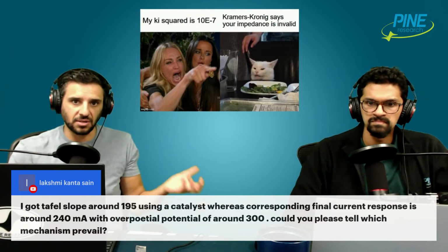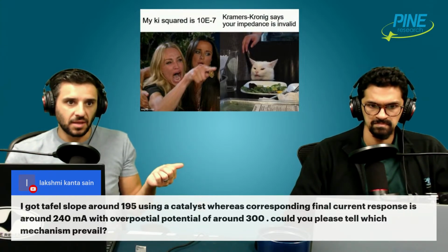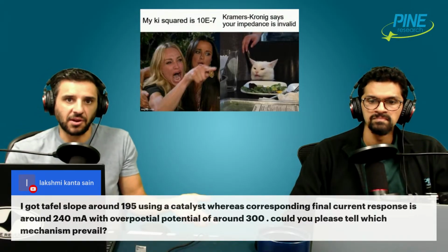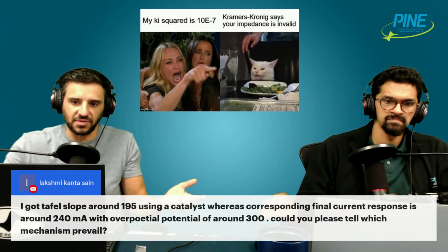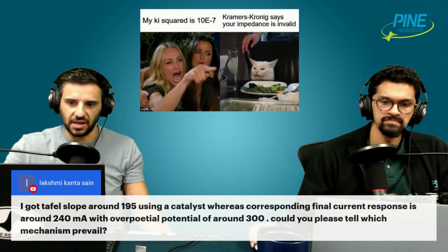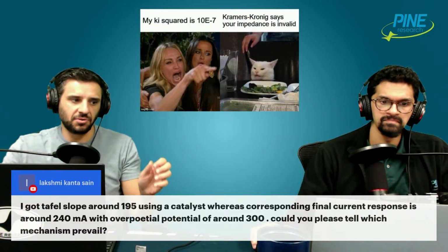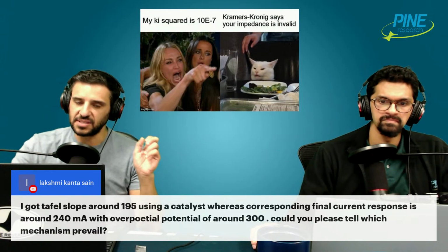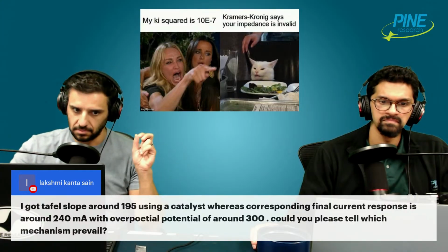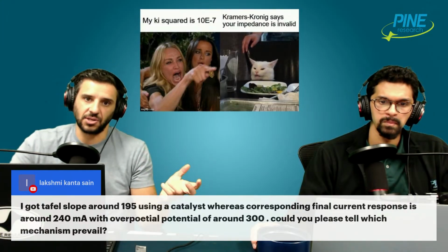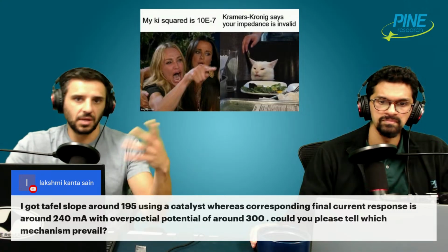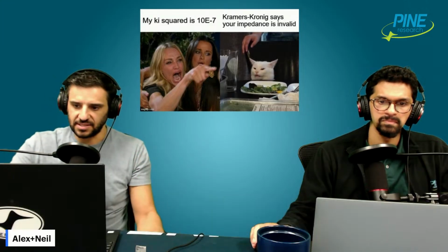And then when you make your Tafel plot, again, there may be errors. It may not be perfectly accurate, but you can trust with a higher degree of certainty than if I just did a CV and then made a Tafel plot. You have a higher degree of certainty that this Tafel plot is really kinetic data. Then I can try to draw conclusions about my slope and mechanism, kinetics, etc.